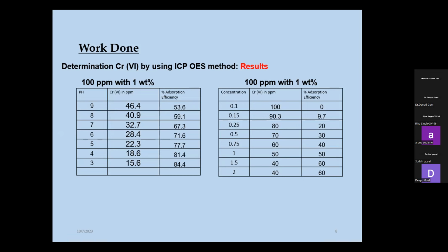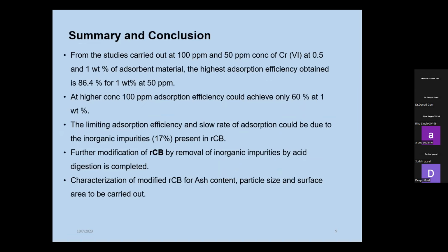In the initial one there is a pH. So in the pH we can see 84.4%, and for the concentration we can see here 60%, and at 60% the adsorption capacity will not change, it will be only 60% we can see. So from the summary, we can see that this activated carbon, which is obtained from the waste tire, is a very good solution as an adsorbent. It can act as a good adsorbent. I didn't show here the result for the activation, but I did the activation, and after activation I got a very improved result, which goes more than 80%. So this is my work.